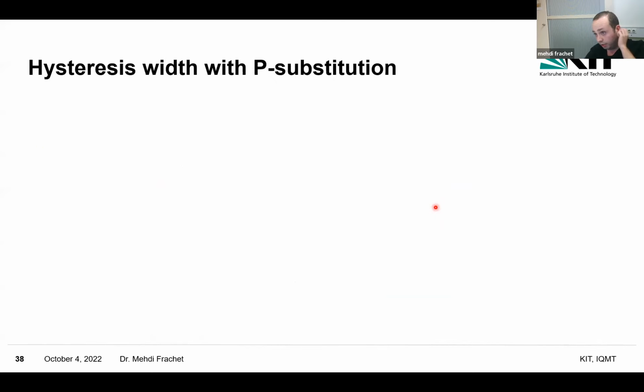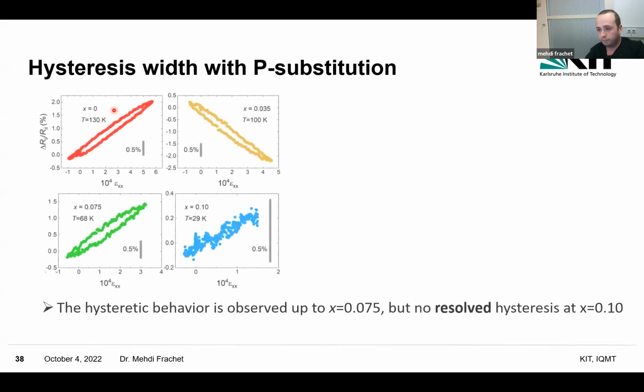But before that, I would like to show you the one thing I already talked about in the undoped compound, which is this hysteretic behavior. So as you can see, we see this hysteretic behavior in the undoped compound. So that's resistance versus strain. But we also observe it in the 3.5% doped sample, 7.5%. But at 10%, we don't see any hysteresis.